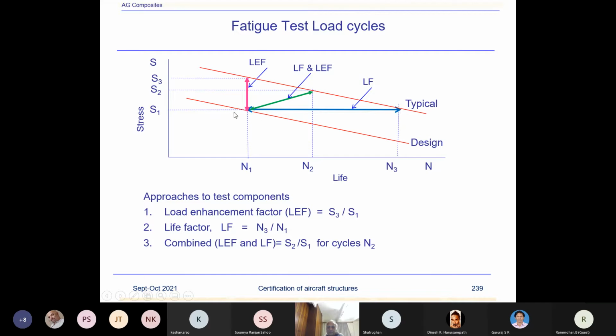That means in order to get at this stress level, we have to apply N3 number of cycles. So that means the life factor would be N3 by N1, which could be 10, 12, depending upon the scatter factor, which becomes high. So rather than applying such a large number of cycles, which becomes impractical for composite structures, the testing is done differently.